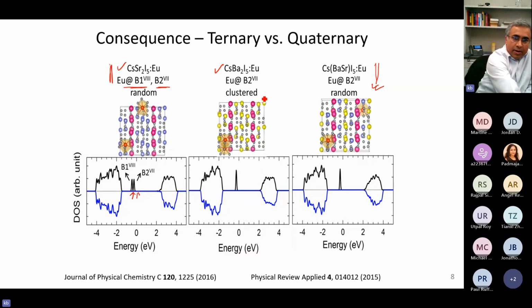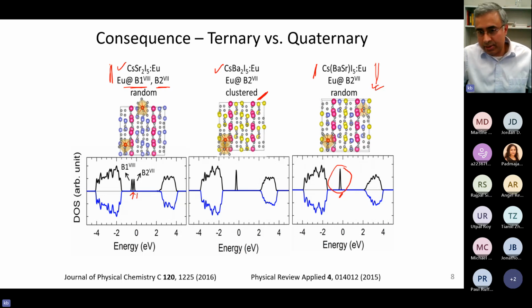And then of course clustering could be a problem in the cesium barium compound. That's why we said when you create an alloy or a mixed crystal of cesium barium strontium, you do not have that problem. You have strontium and europium occupying the strontium site and just the strontium site. So you have just one europium F state inside the band gap, and you also do not have the problem of clustering anymore. So that was our work. I am not 100% sure where the literature is with respect to that. As you can see at the bottom, these papers are pretty old, from several years back. But that was the work that we did, and these are certainly interesting materials.